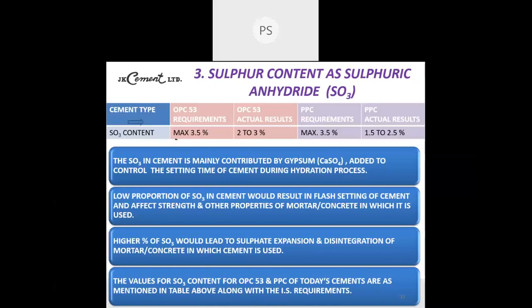Now from the CaSO4, the CaO gets separated and SO3 is released, which joins the SO3 content overall in the cement. Low proportion of SO3 in cement would result in flash setting of cement and affect the strength and other properties of mortar or concrete in which it is used. Higher percentage of SO3 would lead to sulfate expansion and disintegration of mortar or concrete in which cement is used. So SO3 content should be within 3.5, otherwise it will cause the sulfate expansion. The values for SO3 content for OPC and PPC for today's cements are as mentioned in table above along with the IS requirements. Next, please.